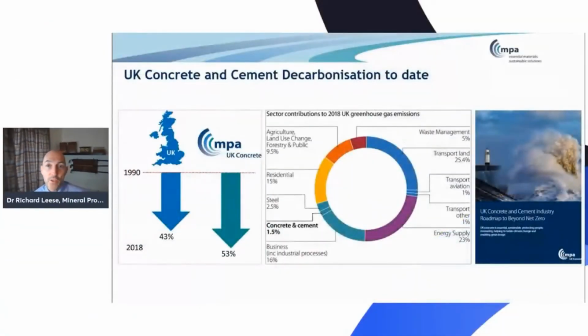Thanks for the opportunity to showcase the exciting developments in low-carbon cements and concretes. I'm Dr. Richard Leese from the Mineral Products Association. The UK concrete and cement industry takes its environmental responsibilities seriously. In fact, the industry is decarbonising faster than the UK as a whole, where the UK as a whole has reduced its emissions by 43% since 1990, and the UK concrete and cement industry by 53% on the same measure. This means that concrete and cement are around 1.5% of the total UK territorial emissions, which is 5 times lower than the global average. But we can't rest on this early action.